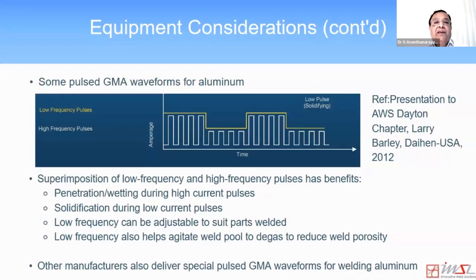And some of the arc welding waveforms are shown here. I'm not trying to recommend one manufacturer of weld equipment versus another. Many manufacturers like Lincoln and Hobart and others also have their own special waveforms for welding aluminum. What they commonly do is to superimpose low frequency and high frequency pulses. Current pulses are shown here.